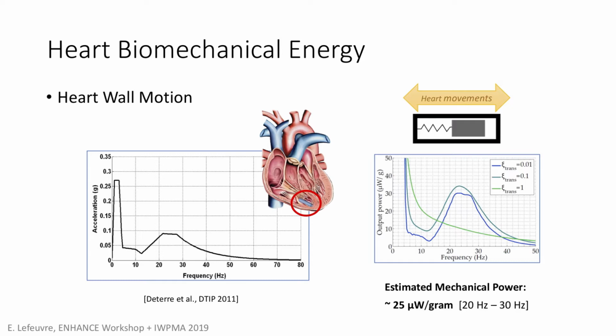Due to the very low frequency here, if we want to really exploit this energy, it corresponds to very large displacements of a few meters. So of course it's not compatible with the dimensions of the heart. But in the range of 20 to 30 hertz, it's more realistic. If we consider 1 gram inertial mass, a rough estimation is about 25 microwatts per gram of inertial mass, mechanical power, sorry. So it's a good way to harvest energy, and that's a large part of the results presented by Professor Skandar-Basrour just before.